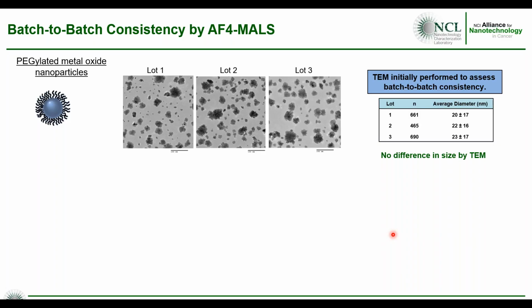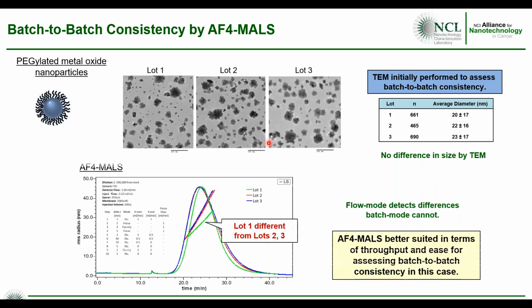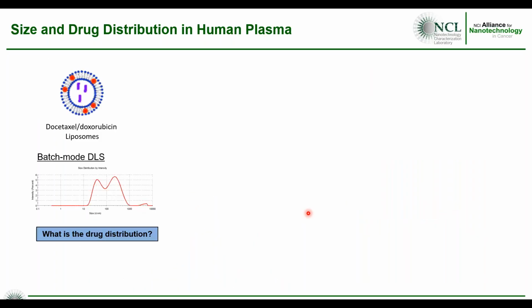And if we went to sizing these nanoparticles by TEM, you can see that they're pretty much the same. So no difference by TEM. So in this case, TEM is not your best method to look at batch-to-batch consistency. However, if we use AF4 with MALS, we can see that actually lot 1 is different from lots 2 and 3. So in this case, AF4 with MALS is better suited to look at batch-to-batch consistency.